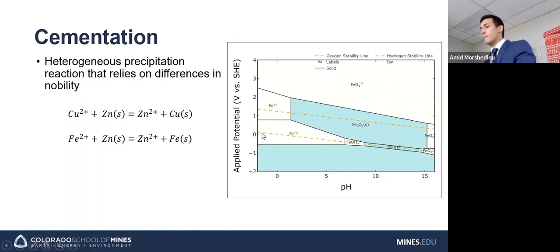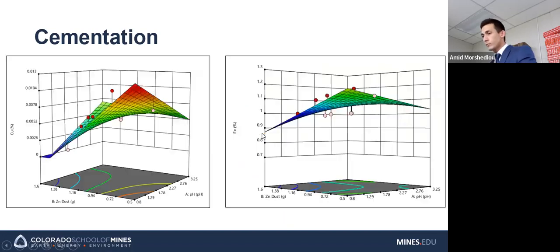And one thing to note, as I talked about earlier, iron is multivalent, right? And so we have Fe3+ and Fe2+. Ideally, we would like iron to be Fe2+. And so what we can do is modulate pH and the applied potential to keep iron in the 2+ region so that we can get better iron cementation.